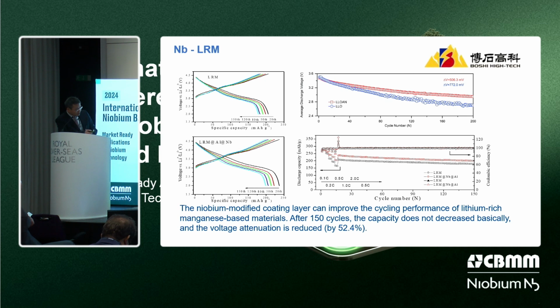We can find that after 150 cycles, the voltage decrease is reduced. The decrease is reduced, and for the capacity, niobium and alumina modified is quite better compared with the one not modified by niobium. Okay, that's almost the understanding we would like to share with all of you.